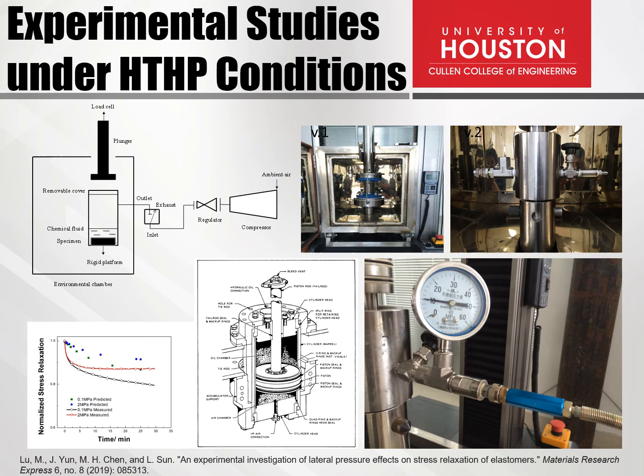To validate the modeling and also study other mechanical behaviors of polymer materials under high temperature, high pressure, and chemically reactive environment, we built a high pressure rating reactor connecting directly to our mechanical test frame, which is capable of performing in situ mechanical testing. The basic idea is to seal the samples and the chemical fluids in the chamber and make the sample ready to be tested before aging. Inner gas is regulated to build pressure inside the chamber.